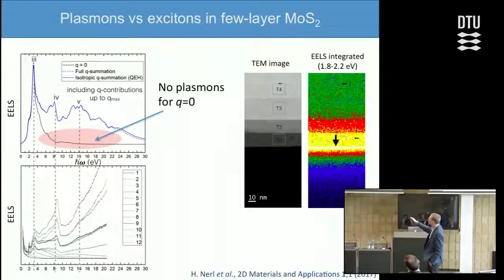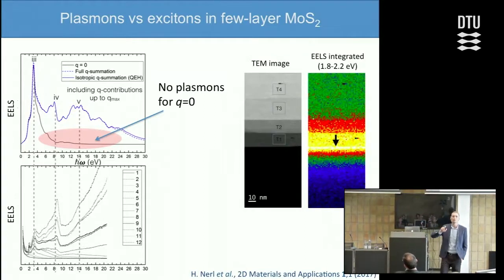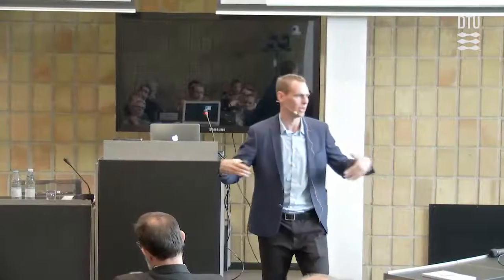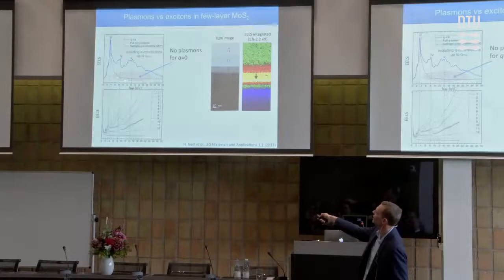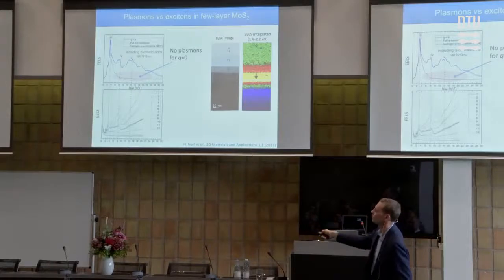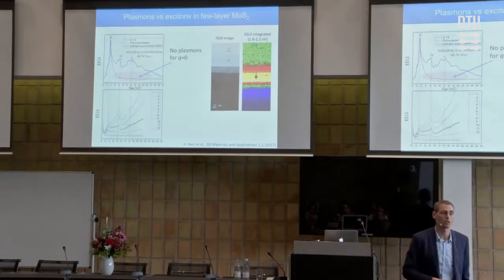If we calculate the EEL spectrum of this material in the Q going to 0 limit, the long wavelength limit relevant in optics where you have photons—photons don't carry much momentum, so you can only probe the small Q regime—then we get the black curve up here, which is completely flat in this energy regime where there's a lot of spectrum in the experimental data.